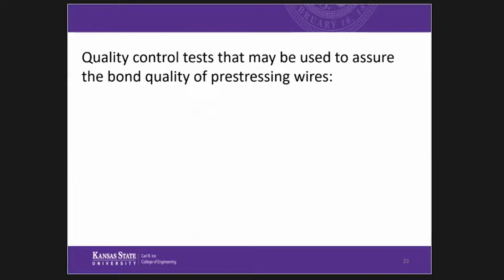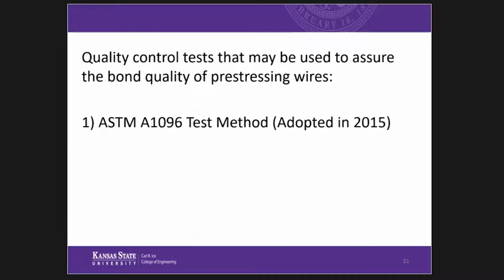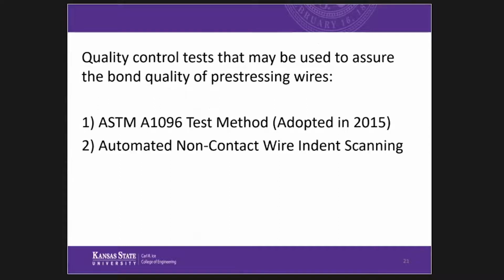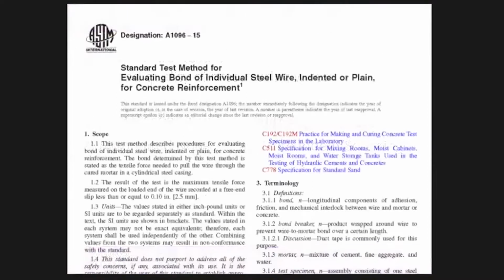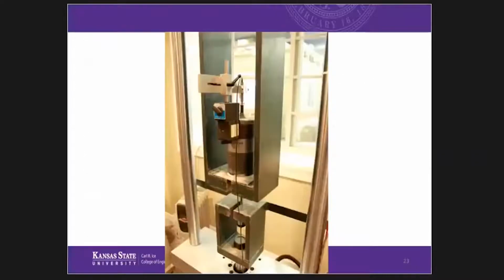The quality control tests that we developed to assure the bond quality, the first one is the ASTM A1096 pullout test method, and that was officially adopted by ASTM in 2015. And the second is an automated non-contact wire indent scanner. So the ASTM A1096, this is the cover page for that document. It specifies a pullout test.